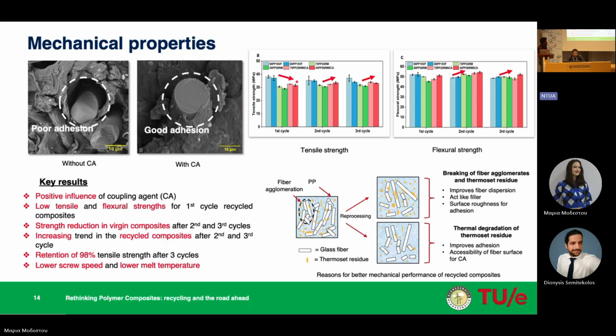One would be the breakage of fiber agglomerates and thermoset residue. As you have already seen, the material which will have thermoset residue on it, and also there is a tendency of these fibers getting agglomerated, which will also affect the mechanical properties of these materials. So while we start reprocessing these materials, there is a tendency for these agglomerates to break into clean fibers, I would say.